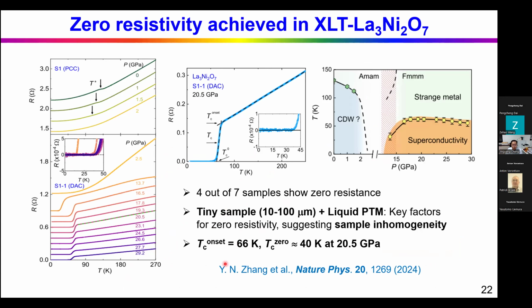Later on, Professor Huiqiu Yuan's group from Zhejiang University also performed the resistivity measurement on the single crystal samples from Wang's group. But here they used a diamond anvil cell with liquid pressure medium, and they measured 7 samples, and in 4 samples they can observe zero resistivity. One of the key factors to achieve zero resistivity is to measure tiny samples, about 10 to 100 micron, and use the liquid pressure medium.